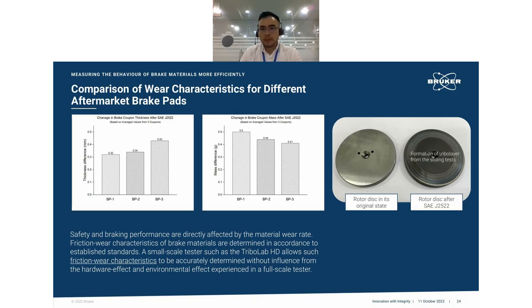We managed to capture the image of the rotor disc in its original state before the test and after the test, where you can see the formation of a ring, which is the tribo layer from the sliding test. You form a tribo layer film on the rotor disc after the test, similar to what happens in our actual brake, in our vehicle.